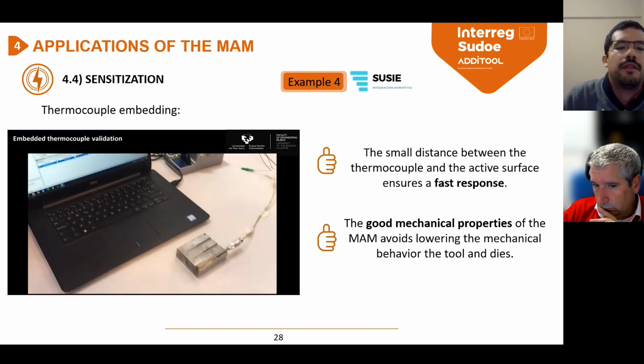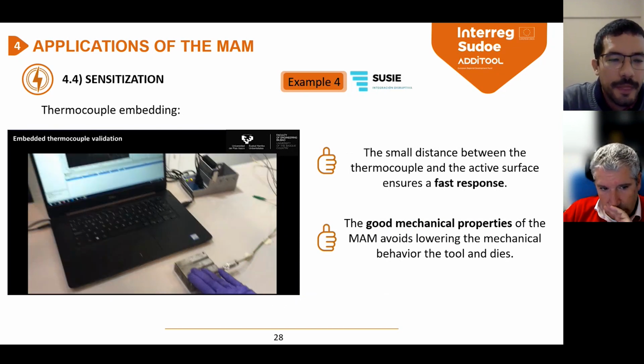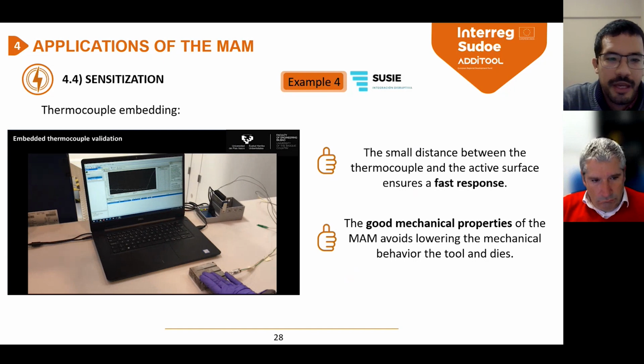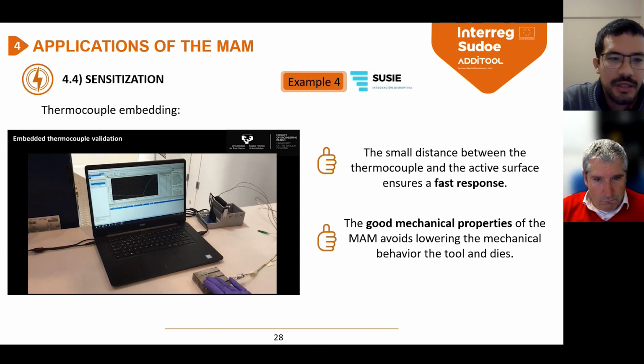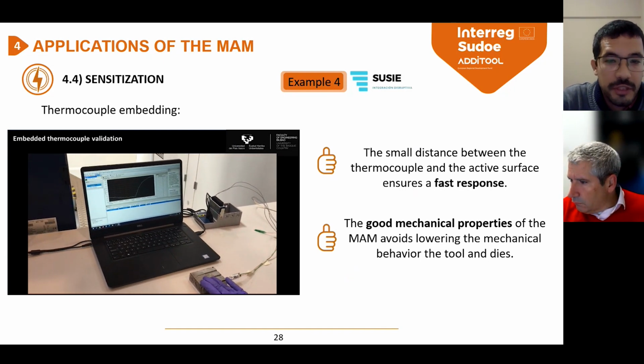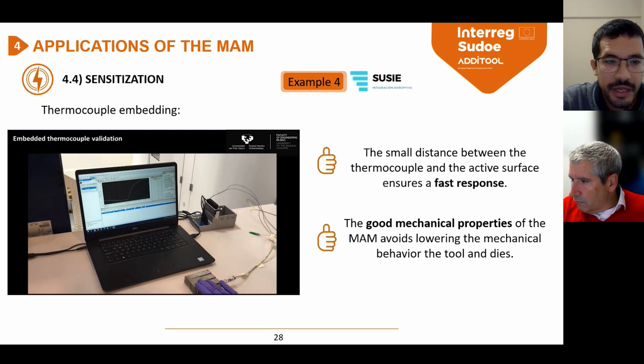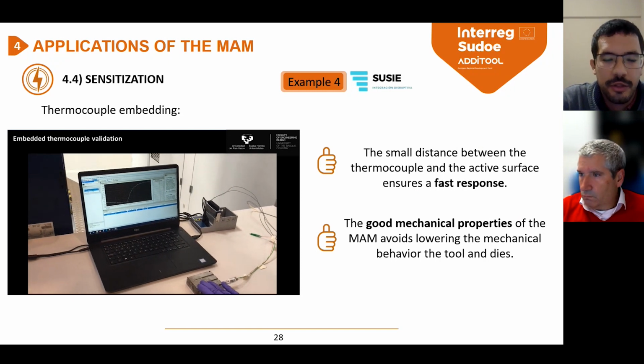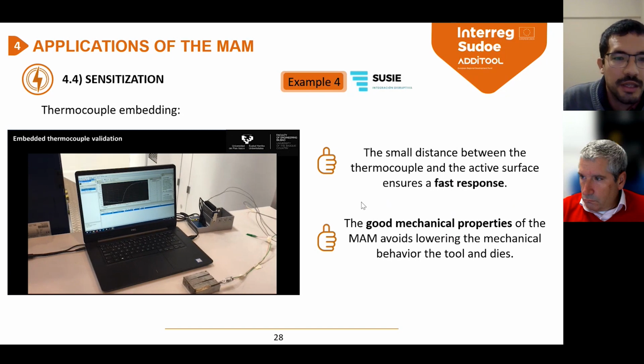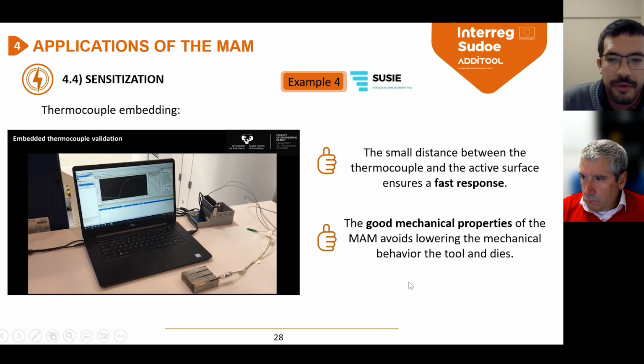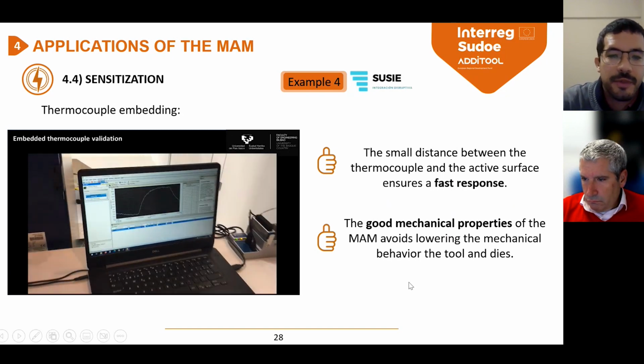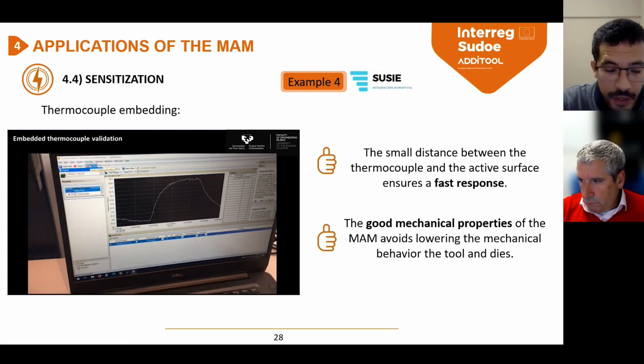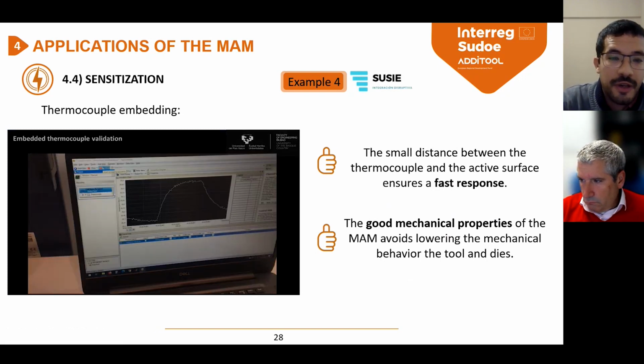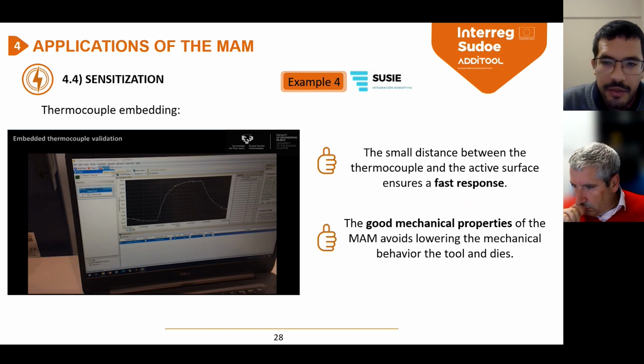The thermocouple was embedded. We analyze its performance by touching directly with the hand, and as you can see in the video, the response of the thermocouple was really fast when heating, and also when the hand releases, it captures really fast the cooling process. And also the mechanical properties of the laser additive manufactured materials are ensured because we deposited the H13, which is a hot stamping tool steel.